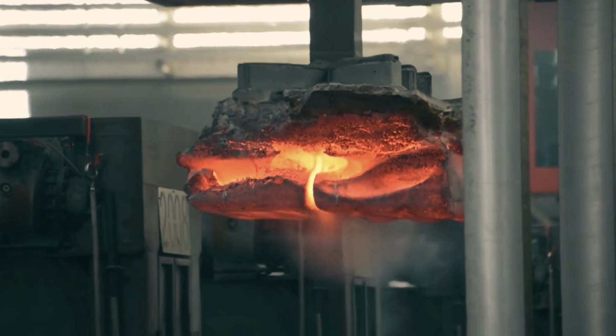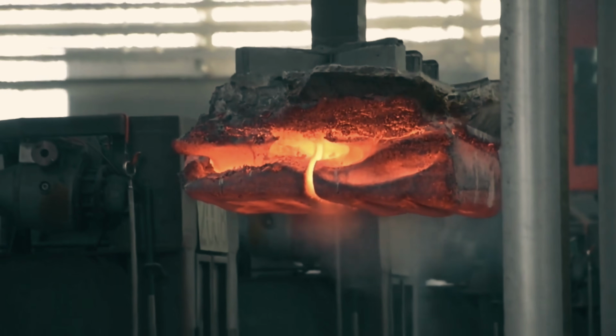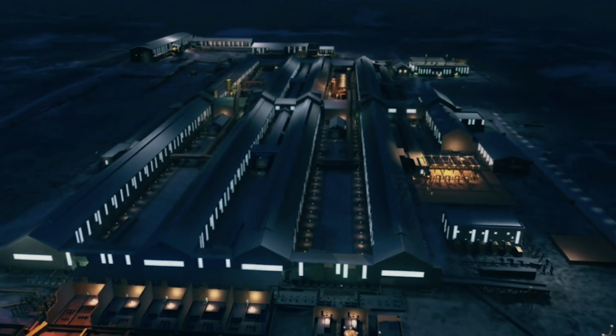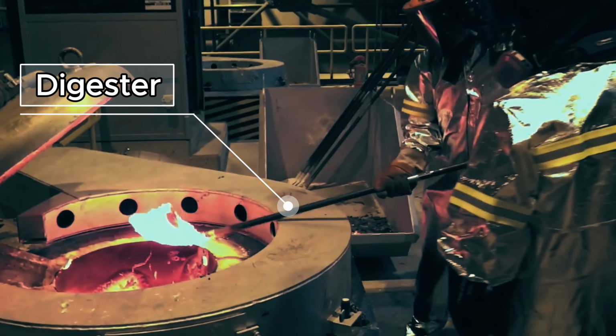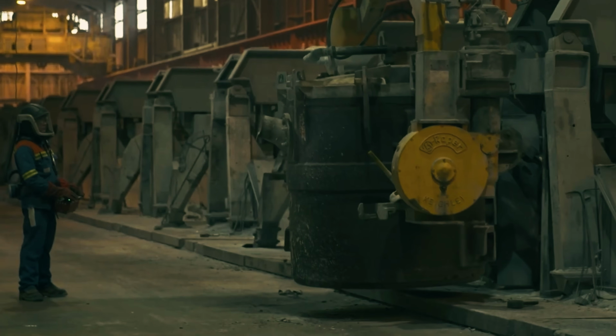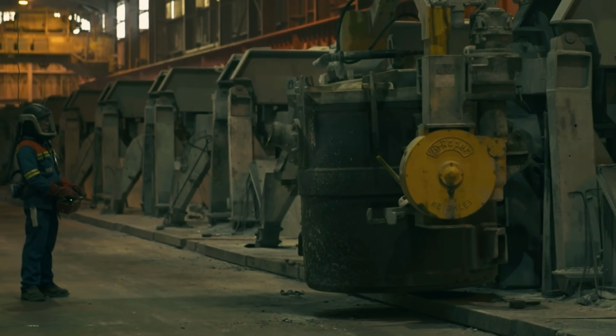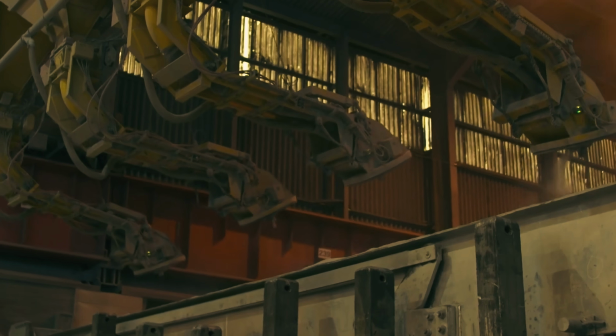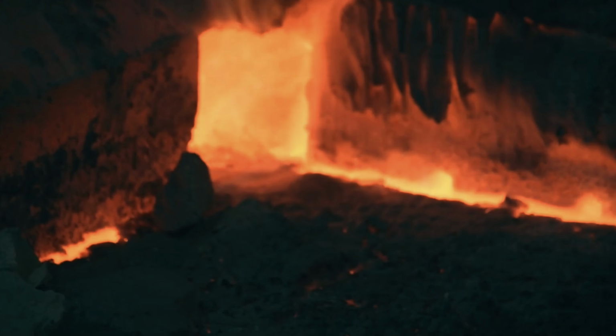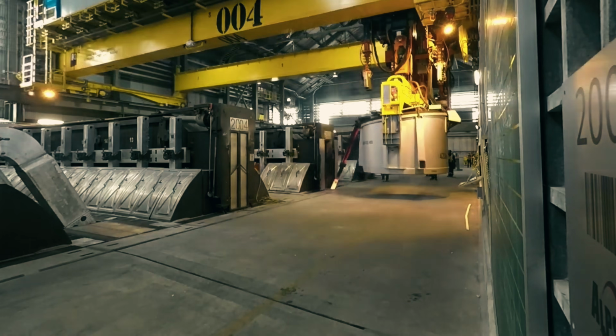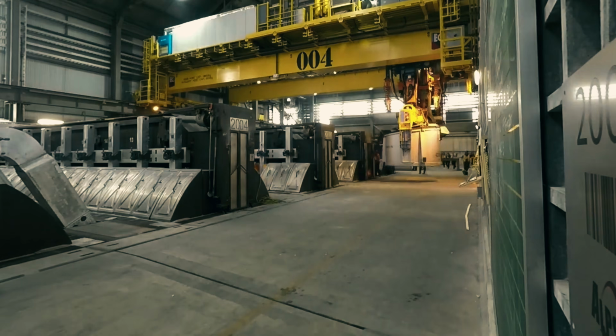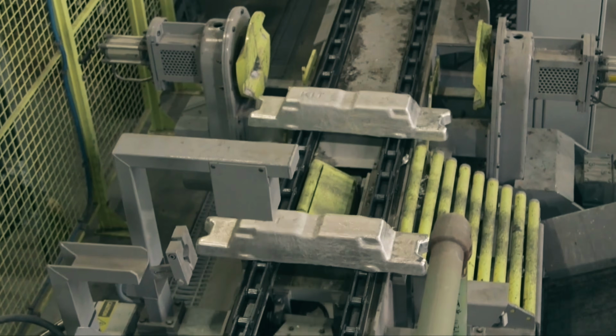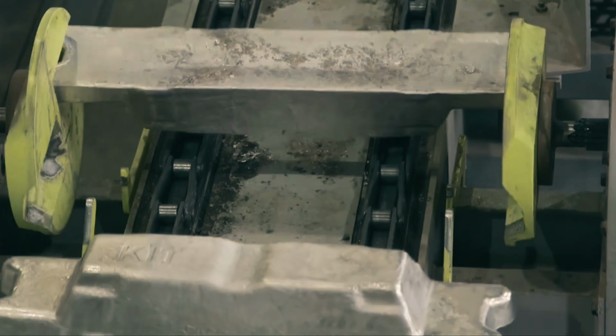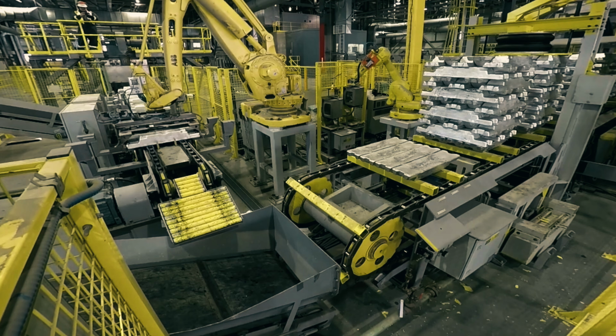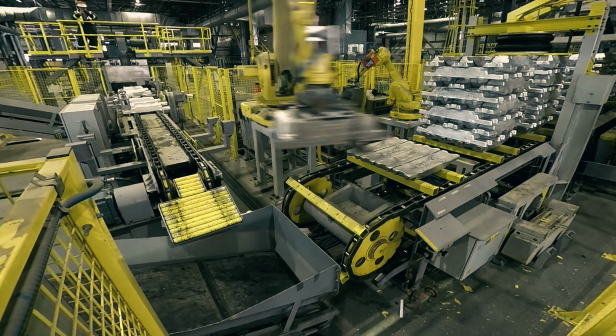The crushed bauxite is mixed with hot sodium hydroxide, essentially a powerful lye solution, inside massive pressurized tanks called digesters, heated to around 270 degrees Fahrenheit. This dissolves the aluminum oxide out of the rock while leaving the iron oxide and other impurities behind as a thick sludge known as red mud. The remaining liquid, now rich in dissolved aluminum, is filtered and cooled until white crystals of pure alumina, aluminum oxide, precipitate out, almost like sugar crystallizing from syrup.